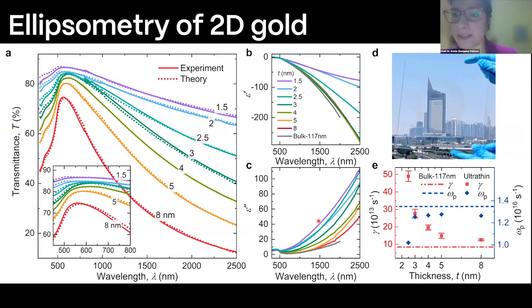And actually, there is another question by Dr. Thomas Wagner. How did you avoid the parameter correlation between thickness and optical constants? It's a good question. For now, we didn't. We know the thickness because when we deposit the gold, we can adjust our quartz calibrator to have exactly the thickness we wanted. So we don't fit it in the optical model.